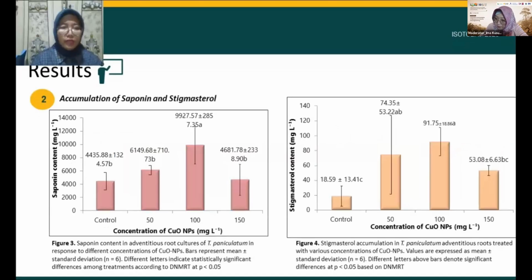2. Accumulation of saponin and stigmasterol. Based on Figure 3 and Figure 4, saponin content increased markedly in response to copper oxide nanoparticle treatment, reaching a maximum at 100 mg per liter. This concentration resulted in more than a twofold increase compared with control. Stigmasterol accumulation followed a similar trend. The highest stigmasterol concentration was recorded at 100 mg per liter copper oxide nanoparticles, followed by 50 mg per liter. Stigmasterol level decreased at 150 mg per liter but was still significantly higher than in untreated groups.